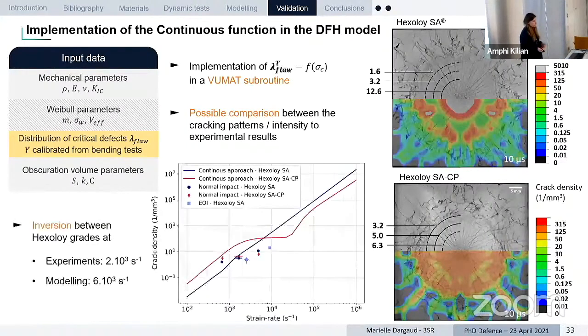When we compare the modeling and the experimental results, we can see that we are in a pretty good range compared to the modeling. However, we can see that at high strain rate, we tend to numerically underestimate slightly the level of cracks. One hypothesis is that in this high rate level, so close to the impact point, the density of cracks is very intense. So with the spatial resolution of the tomography, we are limited to capture these cracks.